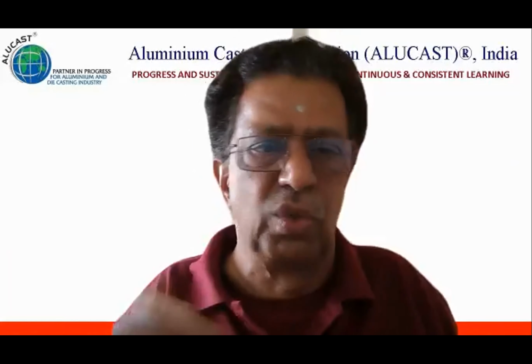Okay. There's a question from Mr. BK Srinivas Rao. Sir, we have customer returns of aluminum components with high oxidation. If we melt them, what is the process defect that will come, or will it have no effect? Well, normally there won't be any effect on the property of the molten metal which is coming out. But with oxidized castings, you will have more melting loss. You may put in 2 kg of casting and end up with 1.95 or something like that. The oxidation loss will be more.